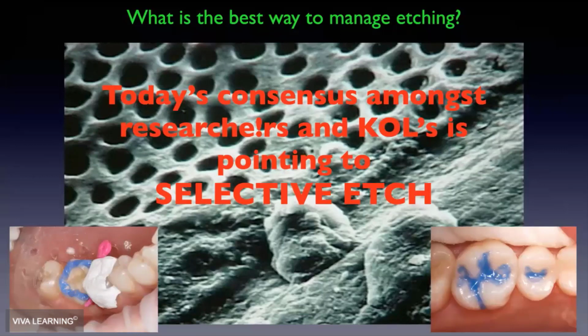And this is what we're talking about. If we have only enamel as a substrate, well, then phosphoric acid does that. And that's what you see in the lower right. If we have only dentin as a substrate, then we're going to use just the self-etching primers, for example, the 6th generation through the universals. However, a lot of the work we do, and especially when we're talking about direct restorations and just meat and potatoes dentistry, posterior composites, is going to be a mixed substrate.